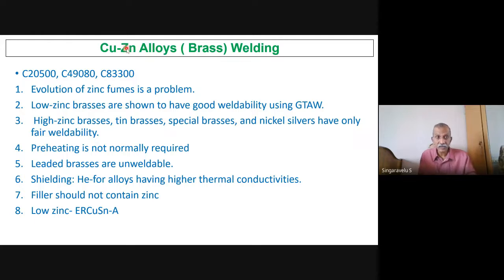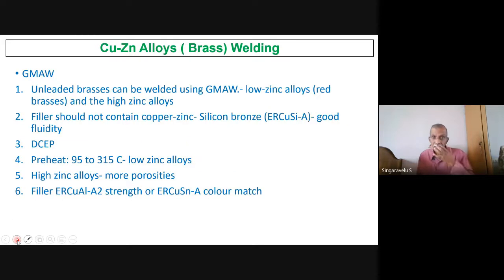Zinc bronzes are a problem because of the zinc. Low zinc bronze can be shown to have good weldability with TIG. Preheating is not at all required. Leaded bronzes are unweldable. Use helium shielding for alloys with higher thermal conductivity, right? Filler should not have zinc. The recommended filler is ERCUSN-A, right? Do the same for brass. You can do it with GMAW, right? Filler should not contain zinc, same thing. Silicon bronze ERCUSI-A is very fluid because of the addition of silicon. Polarity is DCEP, but GMAW has to have a preheat of 95 to 315 for low zinc alloy. High zinc alloy, more porosity, is not recommended.